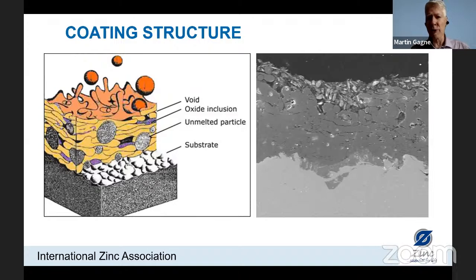Typical porosity or voids in a coating is less than 10%, usually about 5%. And then oxides and unmelted particles can be another 5%. And if we do build up to a coating thickness, normally 100 microns, very similar to hot dip galvanizing, even if there is porosity or voids, they are not interconnected, and there's no through thickness porosity where any corrosive elements can get through to the base steel, even if the thermal spray coating is left on its own.